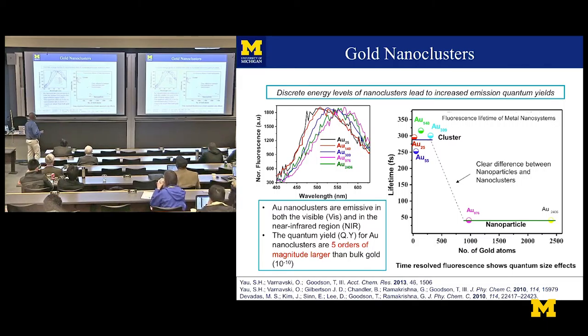And if you look at the lifetime, these clusters kind of all aggregate in hundreds of femtoseconds, and the gold, the big particles, and with surface plasmon are down around 20 to 30 femtoseconds. So it's at least an order of magnitude longer lifetimes. It really is a different emission and absorption process. They are different. And so we wanted to know more.